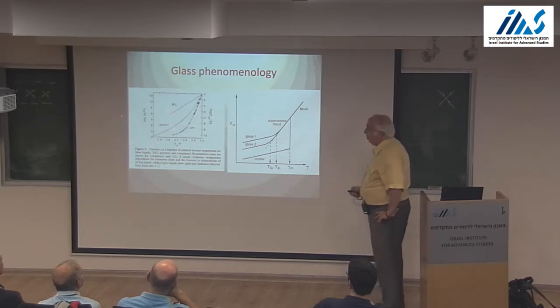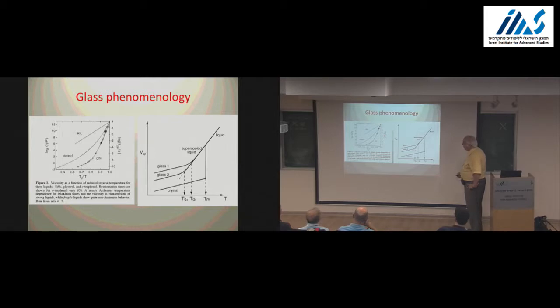This is because the viscosity can shoot up. For example, for glycerol, it can shoot up 14 orders of magnitude within a small range of temperature. This is when the system becomes so viscous that on a human time scale, it's not a fluid, it's a solid. We do know, however, for example in Israel, when you look at Roman glasses from 2,000 years ago, sometimes they have crystallized. So you can sometimes see the phase transition. This is why they are so beautiful, because they have patina due to reflection from the crystal layers. So on a human time scale, you get a solid.